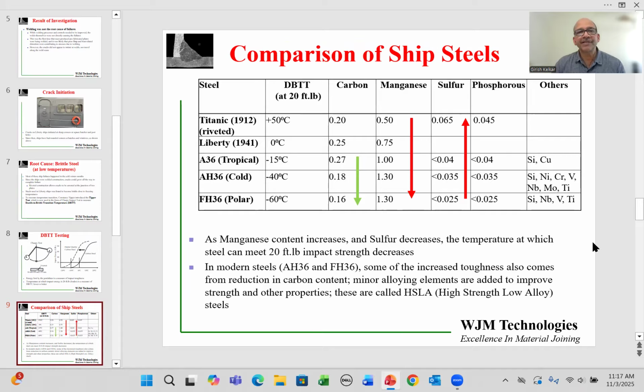No discussion of ship failures is complete without the mention of the Titanic, which sank in 1912. The difference between Titanic and the Liberty ships was that the Titanic was a riveted structure, but it was still affected by the ductile to brittle transition temperature, as it split open much easier than was anticipated. They have done some chemical analysis on the steels from Titanic and the Liberty, and they have actually done ductile to brittle transition temperature testing on the Titanic as well. It was found to be about 50 degrees centigrade positive.